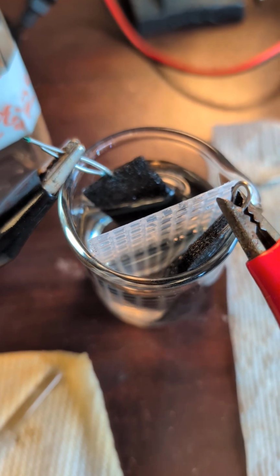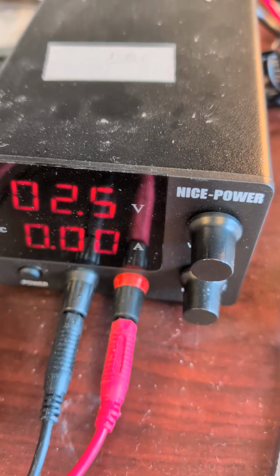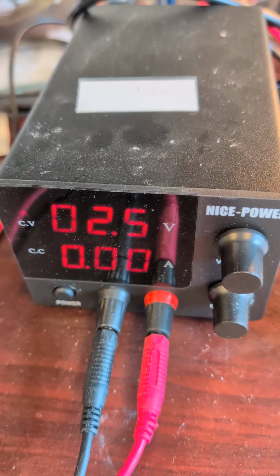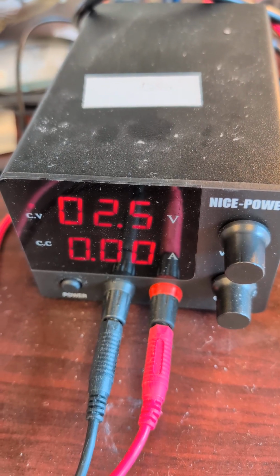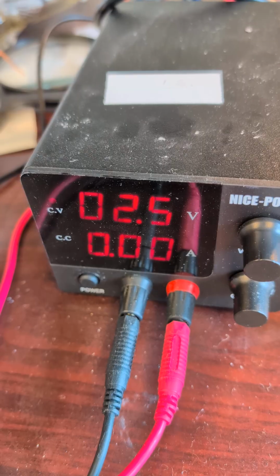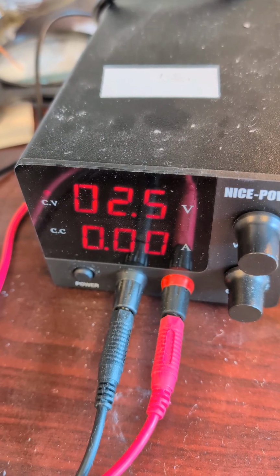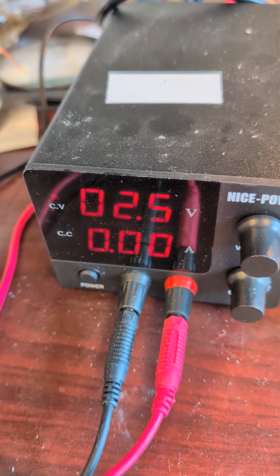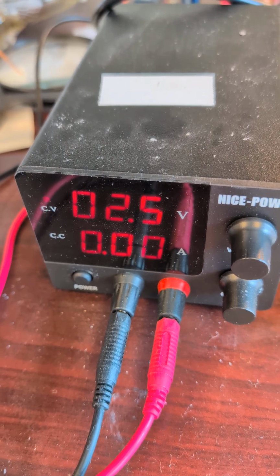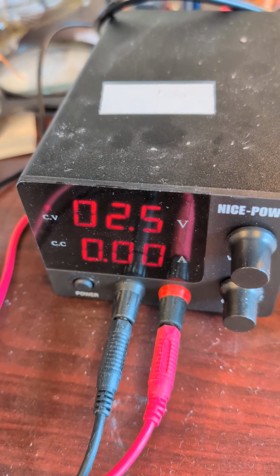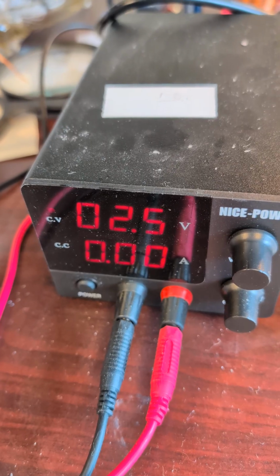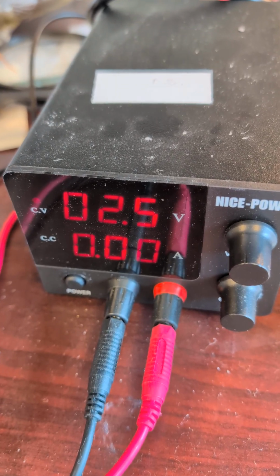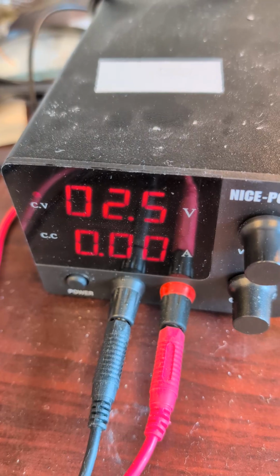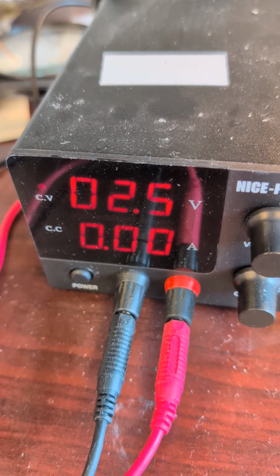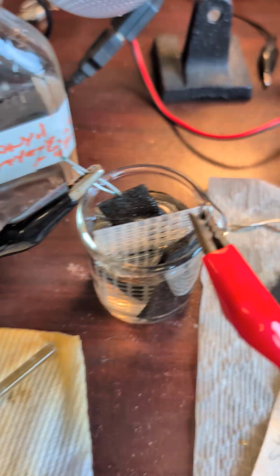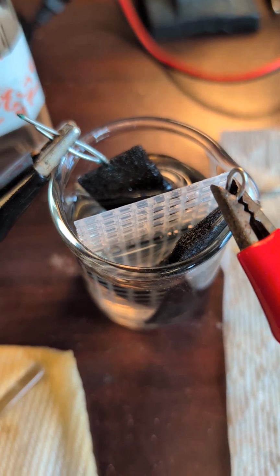No gas evolution. Now, if I boost this up to about 2.6, 2.7 volts, I will begin to produce hydrogen-oxygen gases. So I'm fairly confident at this point that this deep eutectic solvent with water addition, water in DES, I think we call that WiDES, water in deep eutectic solvent. And we also don't have to worry about moisture from the air getting in till you seal the supercap.